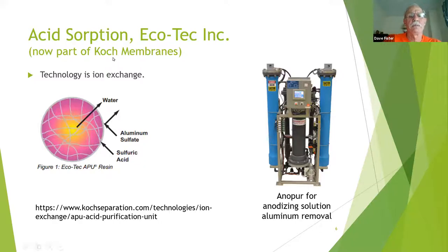So acid sorption, Eco-Tec is a company I've worked with in the past, helping companies in one case with anodizing solution. And this is the example of anodizing. This is their AnoPure system, for removing dissolved aluminum from the anodizing bath. And this is a figure from Eco-Tec where this is the resin bead. You have aluminum sulfate, which is the dissolved aluminum from the anodizing bath, which doesn't get picked up by the resin. And then sulfuric acid, which is picked up by the resin.